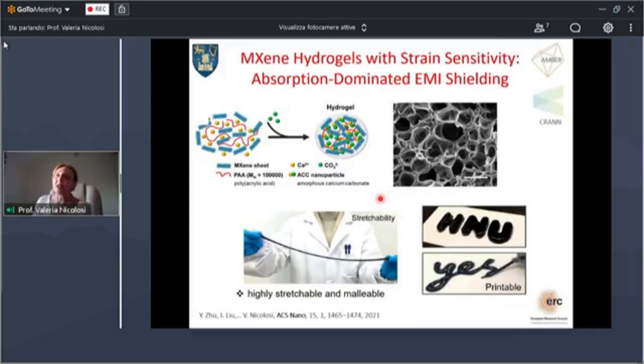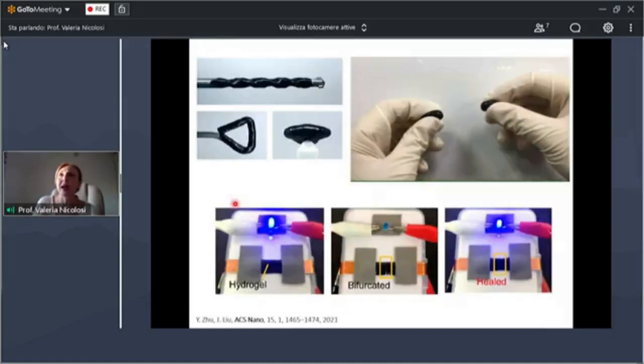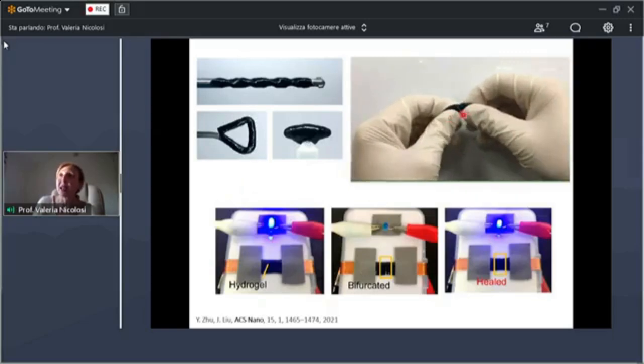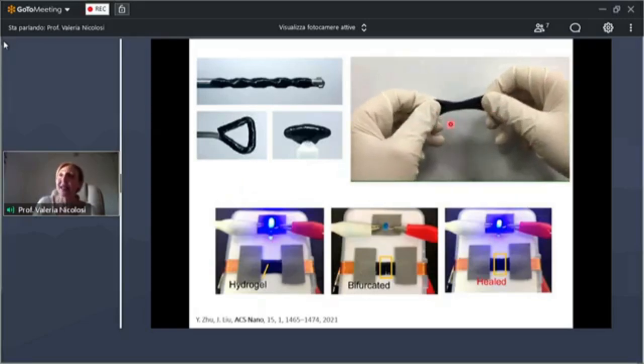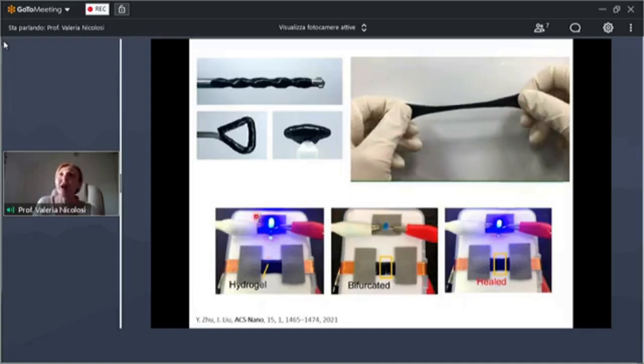Last but not least, I would like to show you a few of the very latest results coming in from my group on a different type of application. We have been using MXenes, mixing them with polyacrylic acid, and we've formed some very interesting hydrogels, which are very stretchable, malleable, and also printable. And they have a very nice porous structure. They are also self-healable. Immediately they heal together. You can see how stretchy, bendable, and healable they are. And they can take basically the shape of the device where they go.